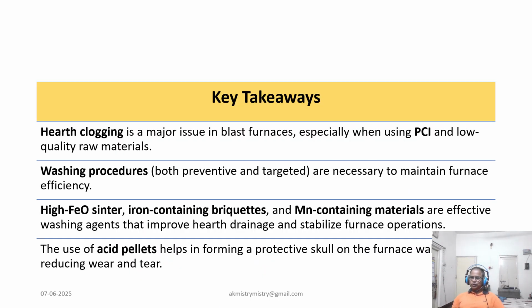So the key takeaway to wrap up is hearth clogging is a major operational threat. Early detection and washing can prevent serious disruptions. Preventive and targeted washing must be integrated into furnace practice. So it should not be something different every day or every week. The right combination of the sinter, briquette, manganese material and acid pellet can significantly improve hearth and furnace efficiency.